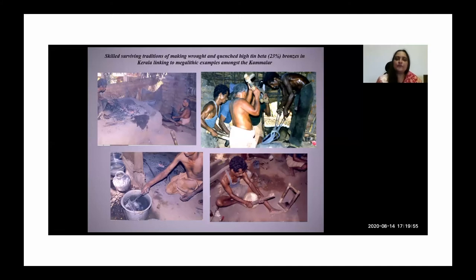And just to take you through the processes of how these vessels were made. So at the top, you see, of course, this documentation was done back in the 90s now, and many of the communities have given up all of this because it's quite laborious and so on. But this is a community of the traditional Kamalar, who are basically a community of braziers or bronze smiths. And as you can see, he is heating a vessel on the flame, which is heated to about 600 to 650 degrees centigrade, and that's what we call annealing, heating in a flame for a long time. And in fact, the gentleman just below the hearth is actually using the buffalo bag bellows to power the furnace. So traditionally, they were not using electrical blowers and so on, but traditional hand bellows.